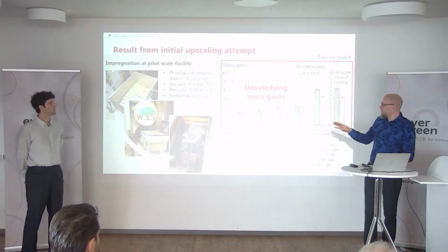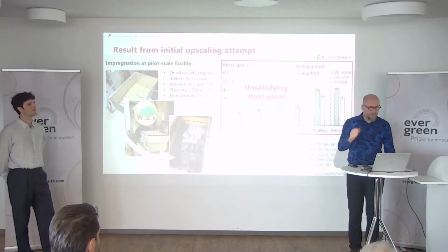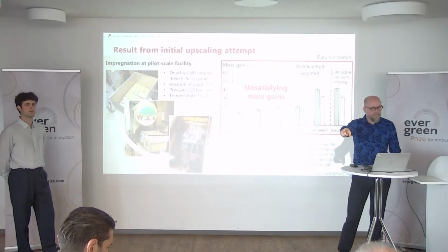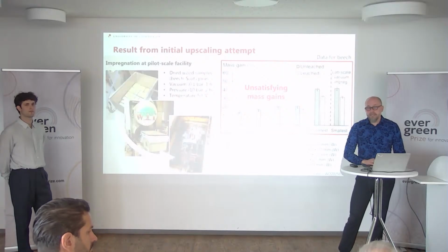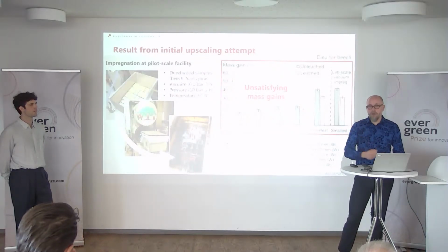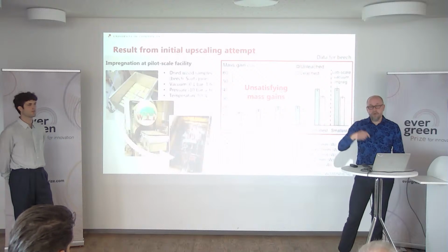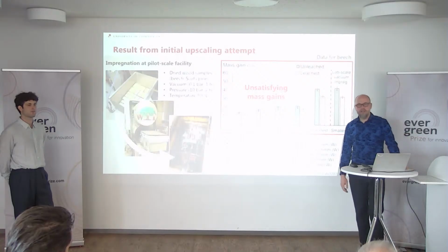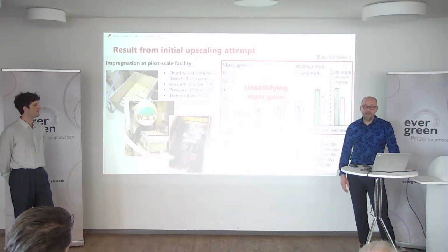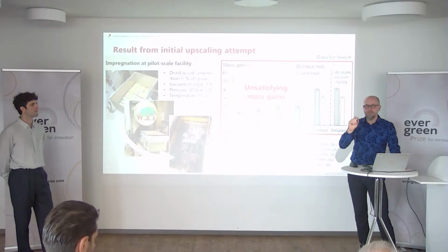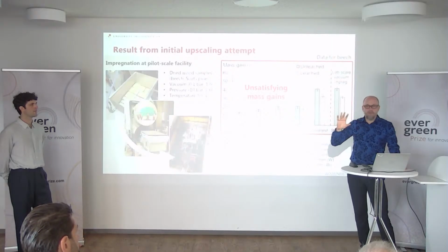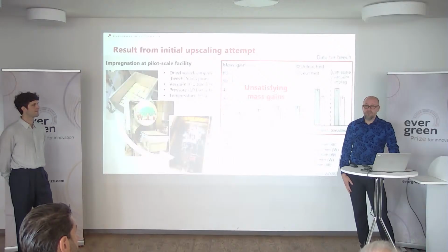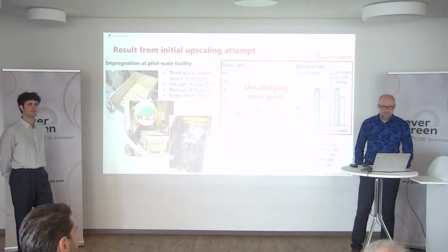And this is unfractionated lignin, like the samples you have in front of you, like the beech, I think, where you have 40% mass gain in these small samples and actually get quite a good penetration. We can see also in the other direction. It's not perfect. We're not there yet, but we have good ideas how to move forward. And I would just like to point out 40% mass gain in the beech. Now we're in a range of densities around 900 kilos per cubic meter. So we are close to durable tropical hardwoods. But of course you're right. It's something that we are continuously doing.